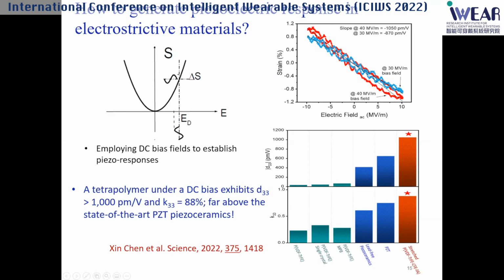In addition, the electromechanical coupling can reach about 88%, which is also much higher than ceramic - PZT ceramic, which is about 75%. So this is the summary. This is the material which we are talking about right now, and this is the best ceramic material with piezo coefficient about 700, and coupling about 0.75. Those are all other early works on PVDF based material - their effects are pretty small.